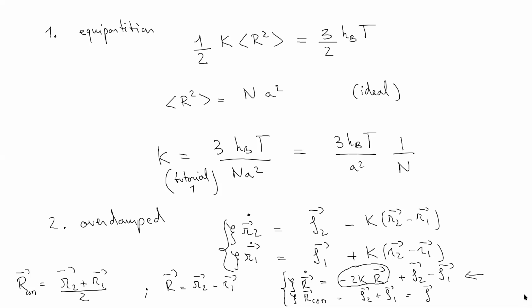What we want to see is that there is a typical time scale associated to that. If you take the average of this equation, the noise terms will disappear, and so you have R and R dot here. So there is a natural time scale that pops in that we can define now. So the time scale associated to relaxation of the internal degrees of freedom can be called tau equals, up to a factor 2, xi over k. Okay, so the damping and the stiffness matters here.